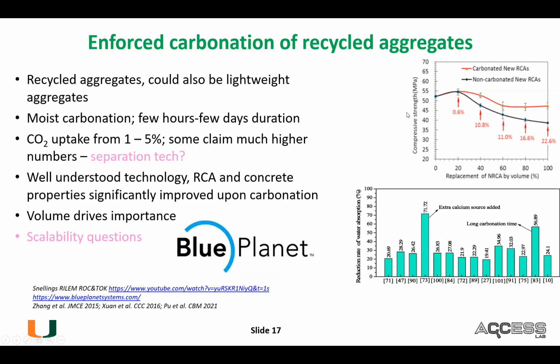Almost everyone just does moist carbonation, where you add a little bit of water. The exposure duration is a few hours to a few days. For the most part, the CO2 uptake here is maybe about 1%, 1.5%. Others have claimed higher numbers, and some are speaking very high numbers, so I don't know how that would be possible.